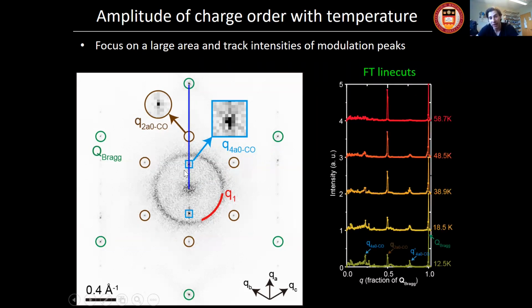If you can warm it up and cool it back down and reproducibly achieve it, that means it's some kind of electronic transition as well. So I'm going to show you this line cut in this topograph as a function of temperature. We focus on the same area of the sample at different temperatures, from 12.5 Kelvin all the way to 60 Kelvin here. And this last peak at 1 is our atomic Bragg peak.